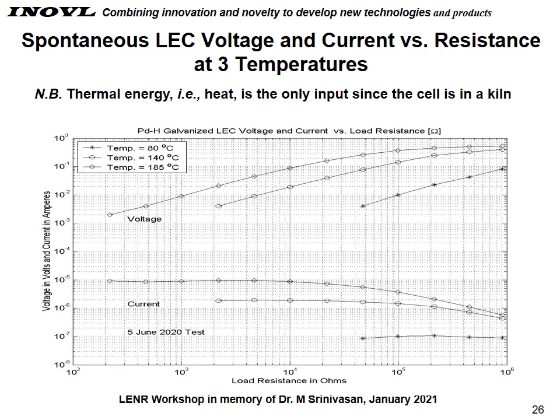This slide shows the cell voltage and current at 3 different temperatures during a load test. You see the temperatures were 80 degrees C, 140 degrees C, and 185 degrees C. At each of these temperatures we would do a load test, and then using Ohm's law we could calculate the current, which we plotted down below. So what you see is the current is fairly constant until you get up to the higher resistance levels, at which point it drops off. So the question is, where is the current going as it drops off?